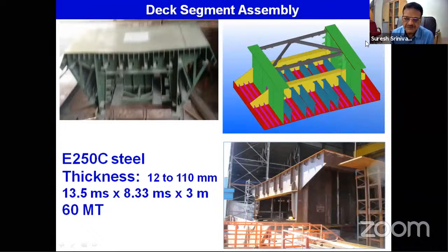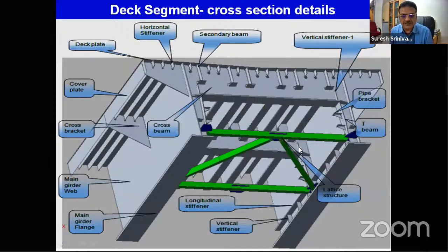In the bottom you have box sections called lattice structure. This is one single segment, which is about 60 tons, and this segment contains about 25 longitudinal joints on the deck plate, about 8 to 10 butt joints in the deck plate, and box sections, lattice structure. Totally about 35 to 40 welded joints in this structure is what you see. And now you can see the Tekla, that is, the solid model drawing of the whole structure. This again clarifies what type of structure it is.